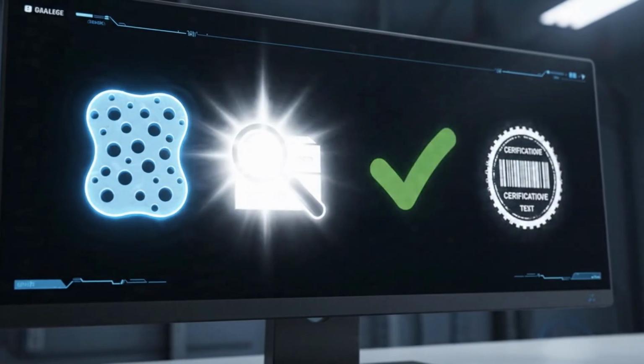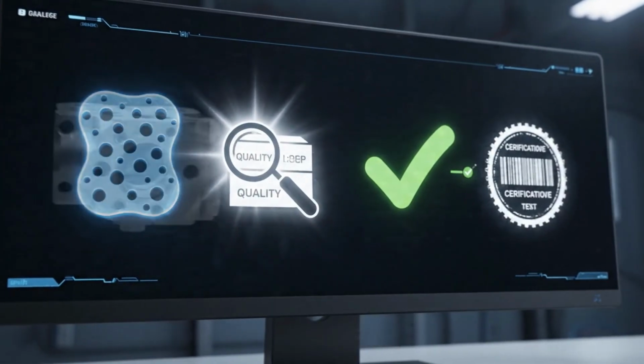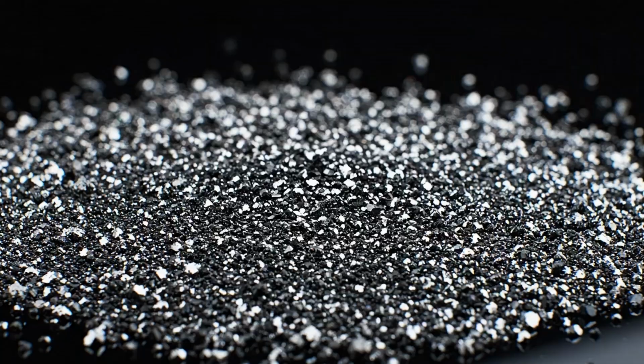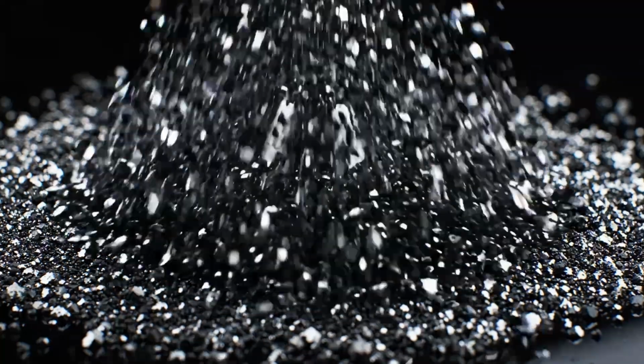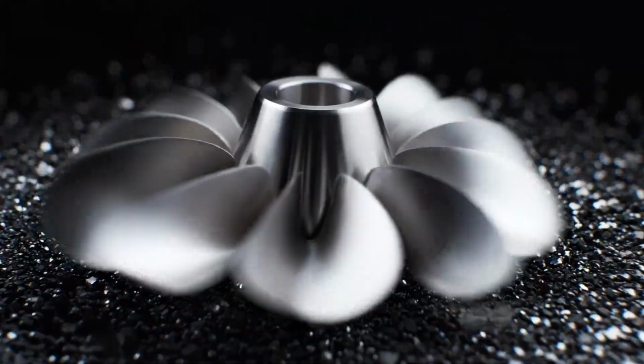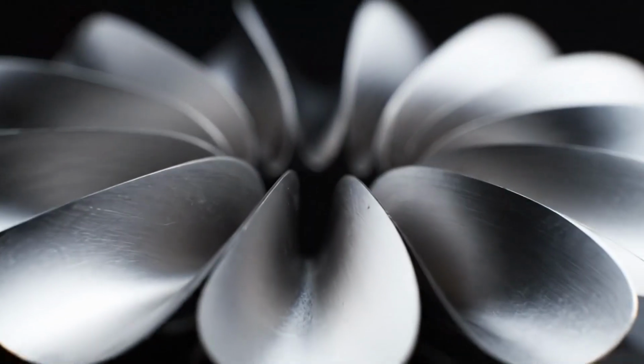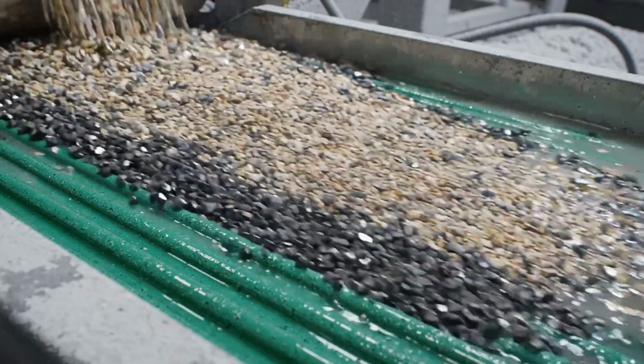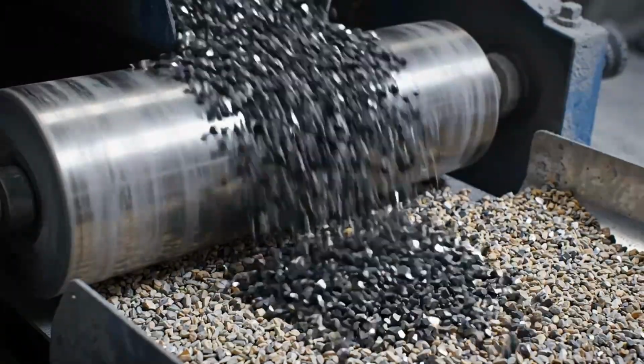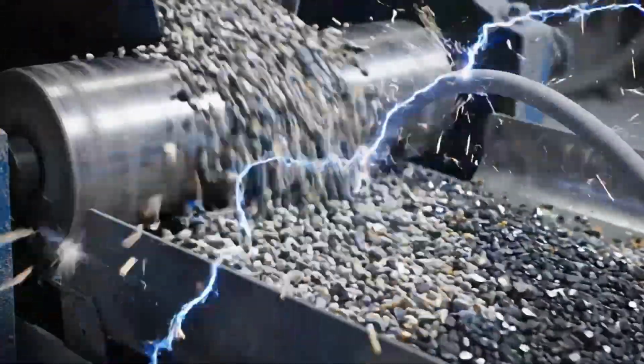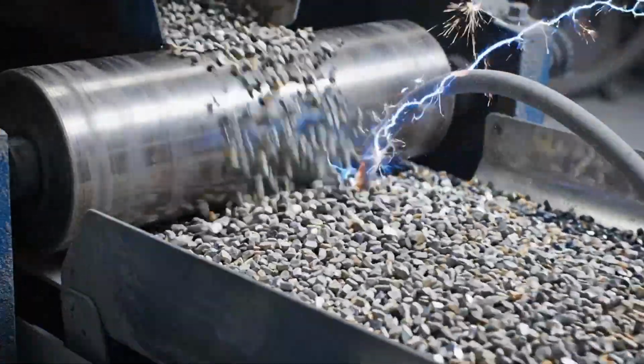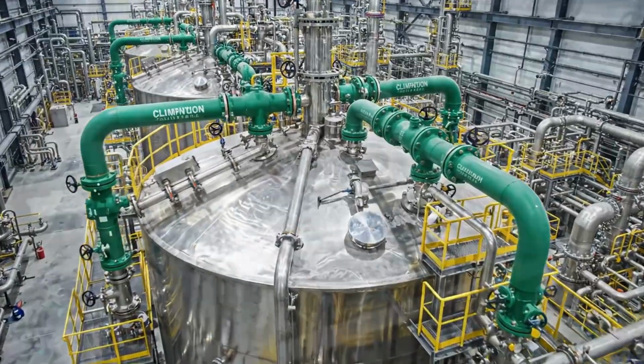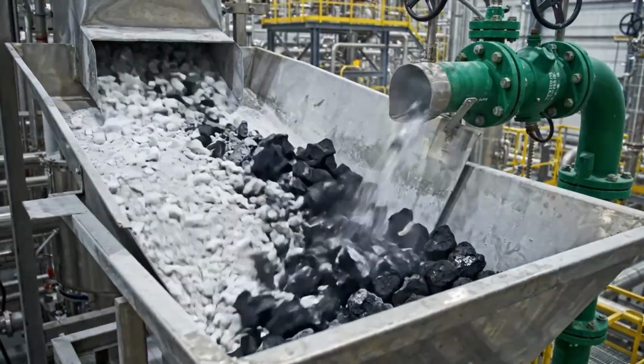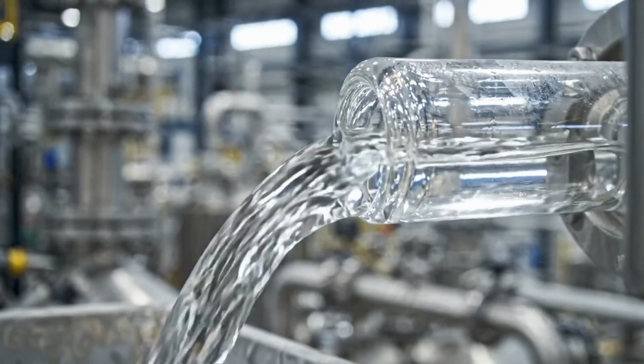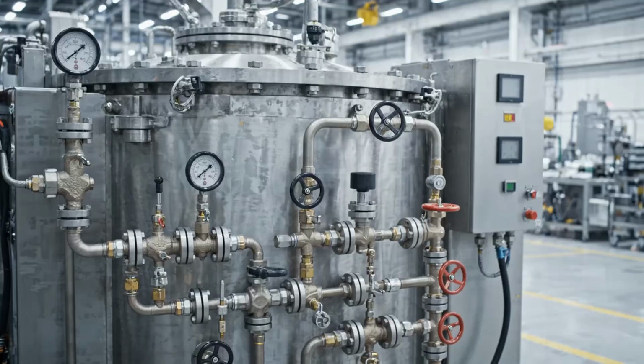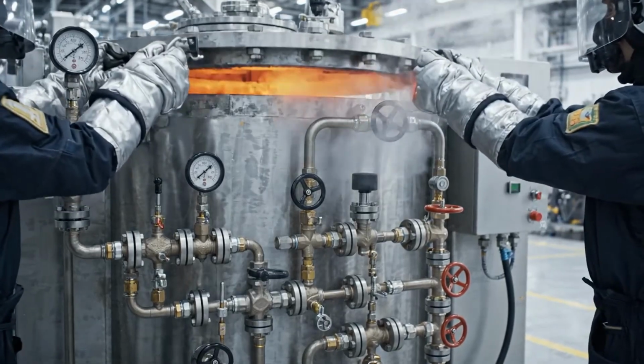The secret of titanium lies in the invisible chain that transforms it from mineral sand into a critical component. First, it is separated from natural deposits using gravity, magnetism, and electricity. Then, it is chemically transformed into titanium tetrachloride. Next, it is reduced with magnesium to form a metallic sponge. Later, it is purified, crushed, blended, vacuum melted, and cast into ingots. Finally, it is forged, rolled, machined, inspected, and certified.